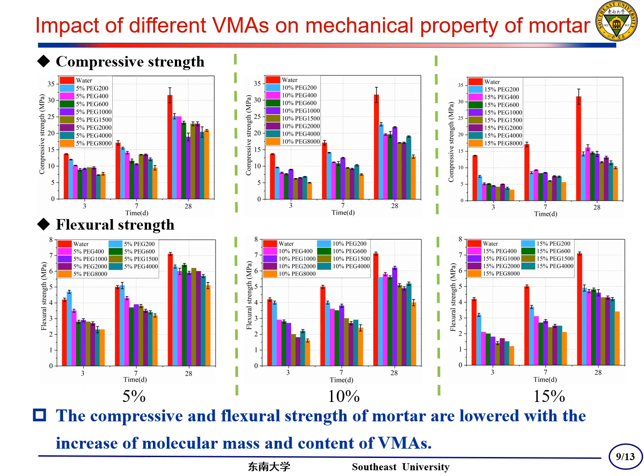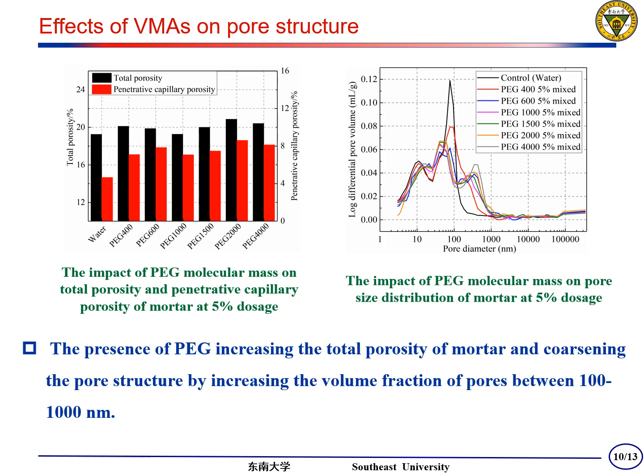For mechanical property, the compressive and flexural strengths of mortar are lowered with the increase of molecular mass and content of VMAs, and the presence of PEG increases the total porosity of mortar and coarsens the pore structure by increasing the volume fraction of pores between 100 to 1000 nanometers.